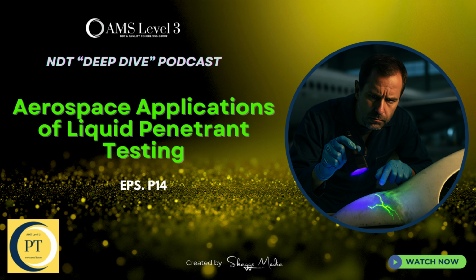Okay, so once it's clean, penetrant application and dwell time, what's the standard environment for this part of the process? For fluorescent liquid penetrant testing, or Type 1, both the part and the penetrant have to be kept within a specific temperature range, usually about 4 to 49 degrees Celsius. That's 40 to 120 Fahrenheit. Application is usually just spraying, dipping, or brushing. And the timing is critical. What are the minimum and maximum dwell times?